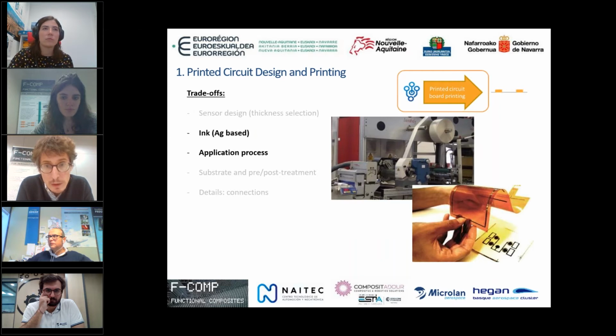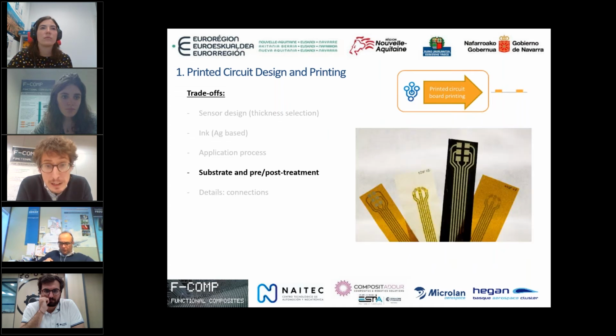As said, this is linked with the selection of the ink. We make a trade-off between different inks that we have in-house as well. NAITEC has very good relations with some companies manufacturing inks here in Navarra. And then we did this trade-off of properties of the ink that as well is related with how we do the process. I mean, we need to prepare the surface material, we need to add additional dielectric material, how many layers, how we put it in the oven. This is very iterative, and mainly related with the substrate that we use.